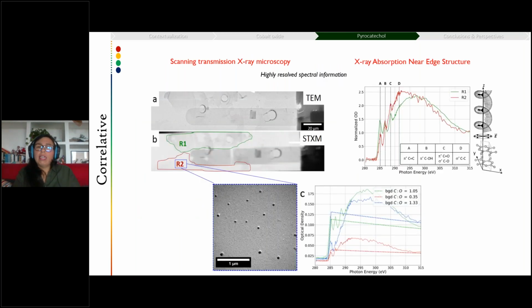Another correlative study that we were able to do was scanning transmission X-ray microscopy, which is a highly resolved spectral technique, performed in this case at the Soleil synchrotron in Paris. This allows us to have spectra at each pixel of the image and correlate this with an optical or electron image, for example.